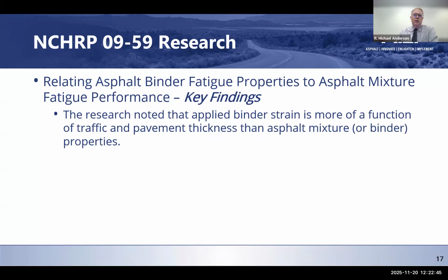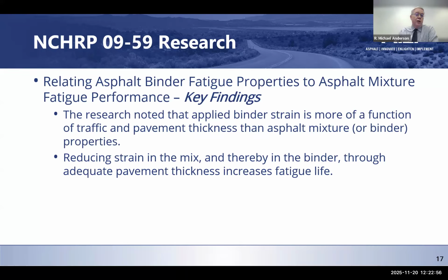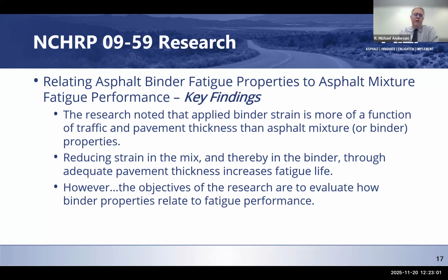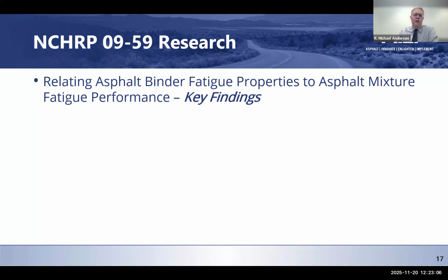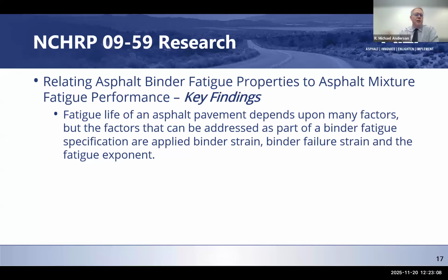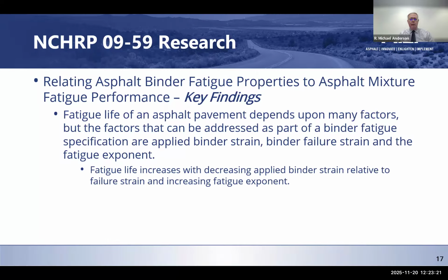So even though they start off by saying binder's not as important as some other factors, because we're using it in a specification, we have to address that. So how do you do that? Well, you reduce the strain in the mix and in the binder through fatigue life, and then eventually you evaluate how those binder properties relate to fatigue. It depends on a lot of factors, but what you can address within a specification are applied binder strain, binder failure strain, and fatigue exponent. We'll talk a little bit about those.